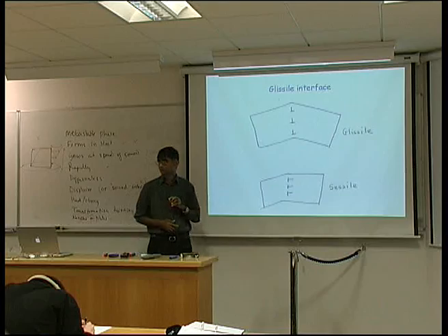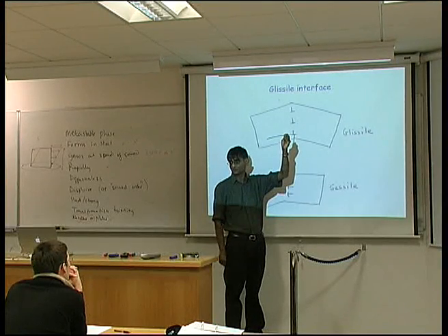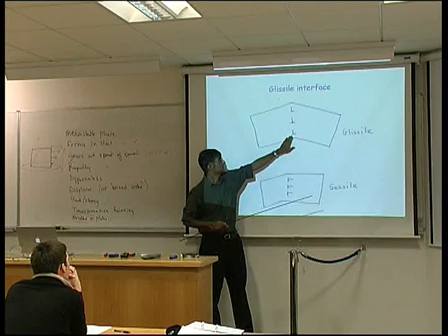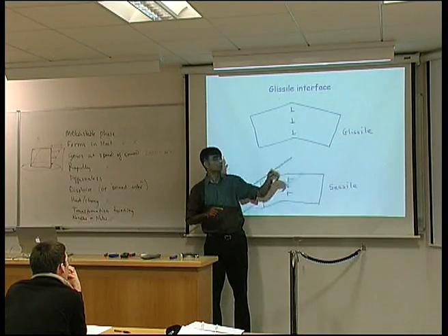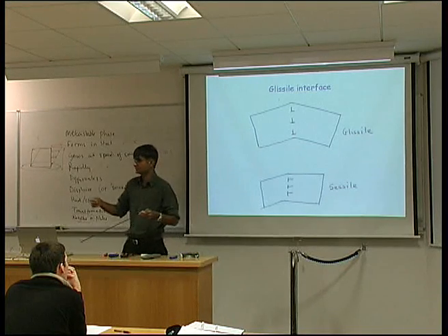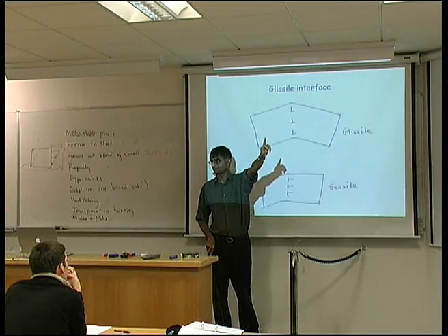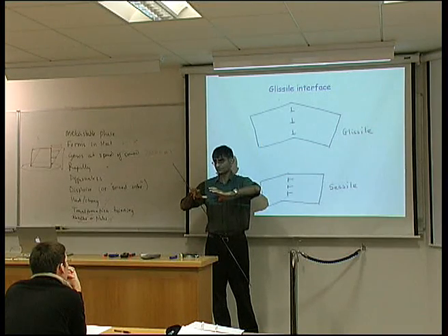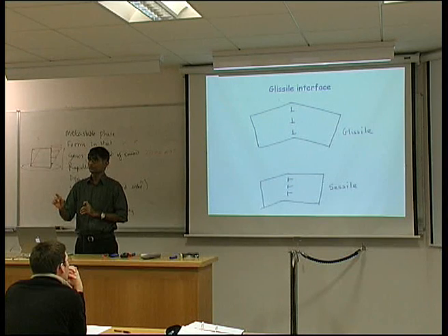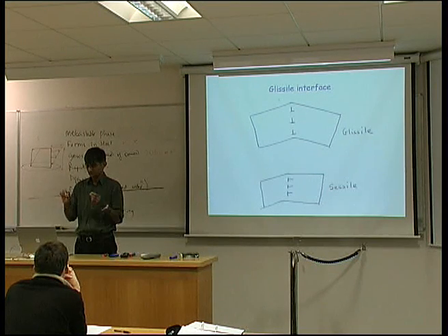I'd like you to look at this diagram, and if you look at the line which is going out of the plane of the board, there must be perfect coherency along that line between the parent and the product crystals, because I have only got one set of interface dislocations here. If there was any mismatch between the parent and the product, then I would have to have another set of dislocations to accommodate that mismatch. Clearly, there can't be any strain along this dislocation line. The two crystals must match perfectly along that line. Are you happy with that? A line like that we call an invariant line. That means it is a line which is undistorted and unrotated between the two crystals.